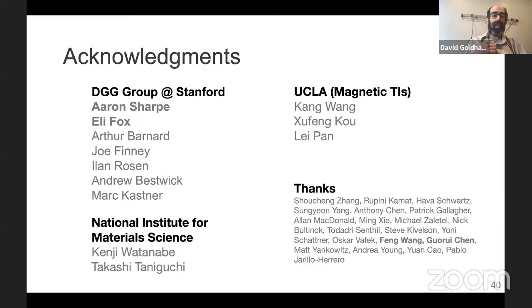And in addition, if you care about two twist angles, the twist angle between the two graphene layers, that's okay, because you can start out, and this was a technique developed by Pablo's group and independently by Emanuel Tutuc's group at UT Austin, what's called the tear and stack technique. You start out with one sheet of graphene, you pick up part of it, then you abruptly pull your stamp off and tear, so that you now have two separate pieces of graphene, but if everything's right, they're still rotationally aligned.